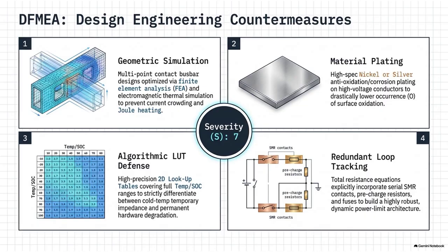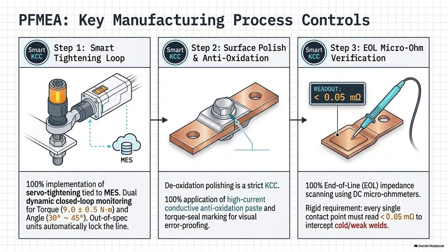That is wild. But even with perfectly engineered, squishy microbumps, you still have the issue of oxidation over time if the bolt relaxes even a fraction of a micron, right? You get that copper oxide crust. Which leads to the material specification countermeasures. Bare copper is completely unacceptable in these critical high-voltage joints due to the insulating properties of copper oxide. The DFMEA mandates high-specification plating, specifically nickel or silver plating, over the copper bus bars.